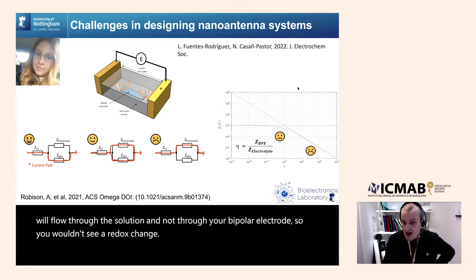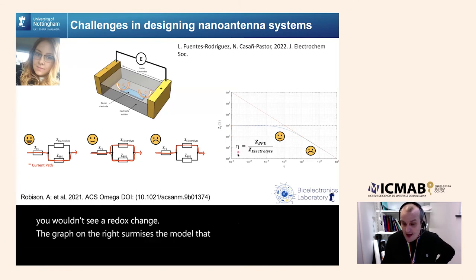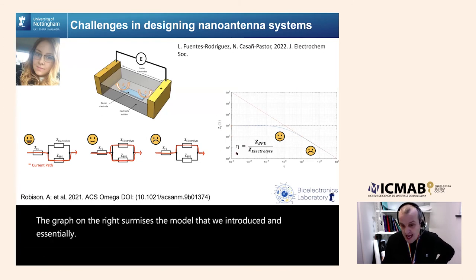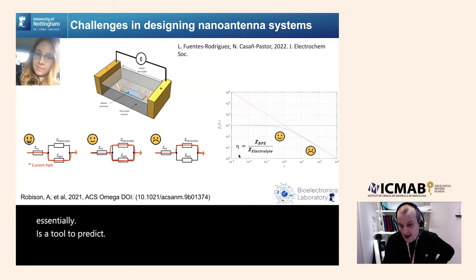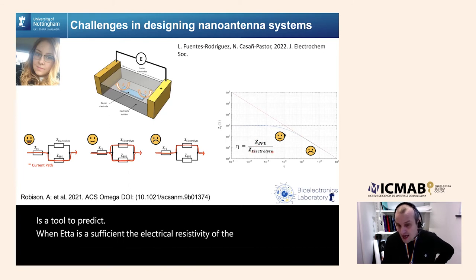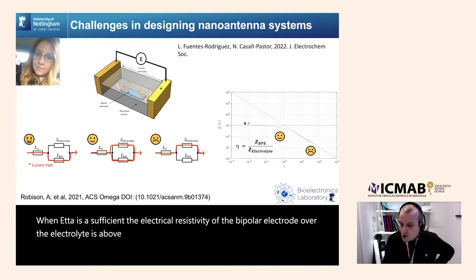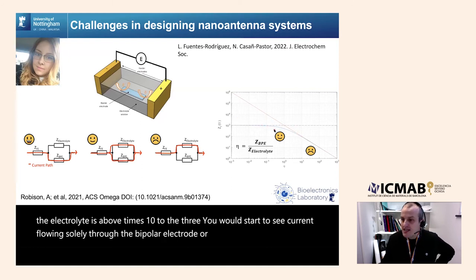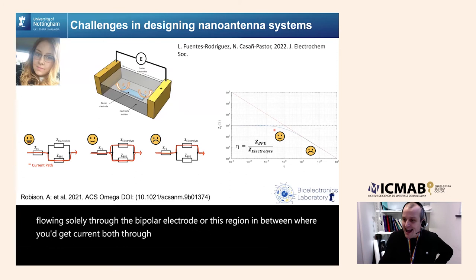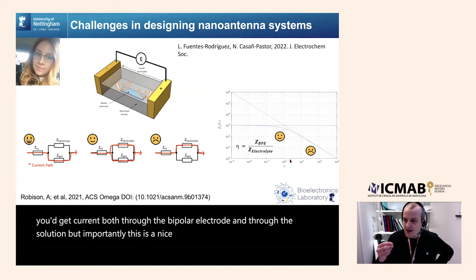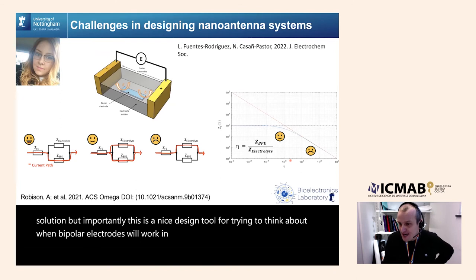The graph on the right summarizes the model that we introduced and essentially is a tool to predict when eta is a sufficient ratio. When the impedance, the electrical resistivity of the bipolar electrode over the electrolyte, is above 10^3, you would start to see current flowing solely through the bipolar electrode, or this region in between where you'd get current both through the bipolar electrode and through the solution. But importantly, this is a nice design tool for trying to think about when bipolar electrodes will work in biology, because biology is inherently an electrolyte.